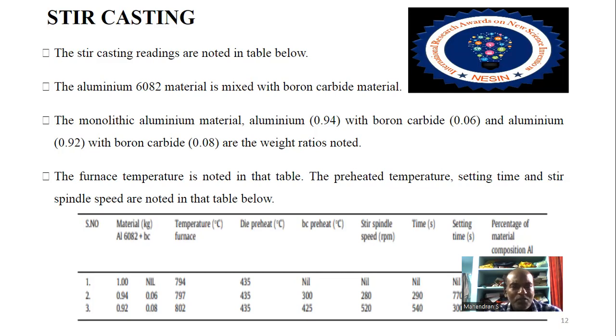The furnace temperature is noted in the table also. The preheated temperature, setting time, and stir spindle speed are noted in the table below. There is material one, aluminum 6082 plus boron carbide 0.94, 0.92. These are the various fractions added. Aluminum 6082 plus boron carbide. The furnace temperature is noted as 794, 797, 802, and so on. The table indicates the die preheat, boron carbide preheat, stir spindle speed, time, setting time, and the percentage of material composition.